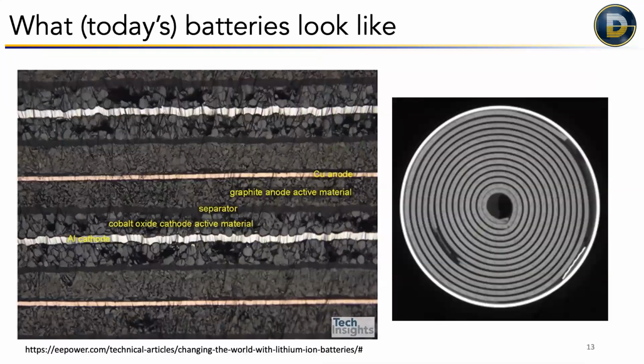But if you look at the stack, it looks something like this, where you can see the metal foils here. So you have an aluminum foil on the positive electrode side, you have a copper foil on the negative electrode side, and then you have a polymer separator that spaces them out. But this is porous like a sponge. So the liquid electrolyte that fills all of the pore space in this whole structure can permeate through the separator and into the electrodes. So then when you connect your light bulb or whatever you're going to power to these current collectors, you have a voltage and you can do useful work.